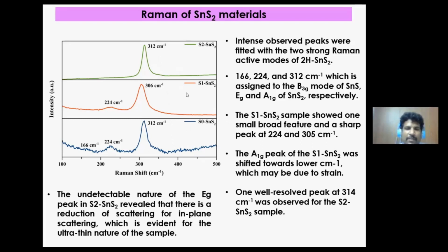Okay, so all those 3 samples, the base material of all those 3 samples is SnS2, so that is confirmed first. And then we found that generally 166, 224, and 312 centimeter inverse, which are assigned to B3G of SnS and the EG and the A1G of SnS2. So the B3G mode that is observed for S0 SnS2 is at 166. The intensity of this peak is very, very small. So in the combination of SnS and SnS2, the SnS2 may be in large amount, so SnS may be a very little amount. In XRD also we have confirmed.